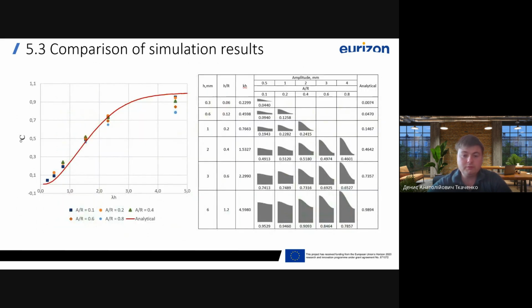For quantitative comparison, the curves were linearized using the least square method. The results confirm that the assumption of a smooth free surface holds for a wide range of cases. For moderate and thick films, the analytical solution is reliable up to a relative initial amplitude of 40%, with errors below 10%. However, for thin films, significant disparities appear, with the numerical model predicting a faster smoothing rate unrelated to the free surface smoothness.